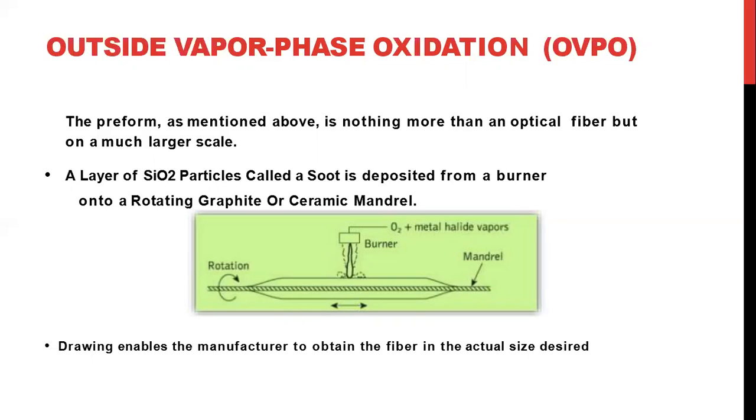In this method, a mixture of oxygen, silicon tetrachloride, that is SiCl4, and possibly other substances like rare dopants is passed through a rotating silica glass tube, which is heated from outside in the range of 1600 Celsius with a flame. Towards the end of the process, the gas mixture is modified to form a layer with higher refractive index. Finally, the tube is collapsed by heating it to 2000 degrees Celsius.